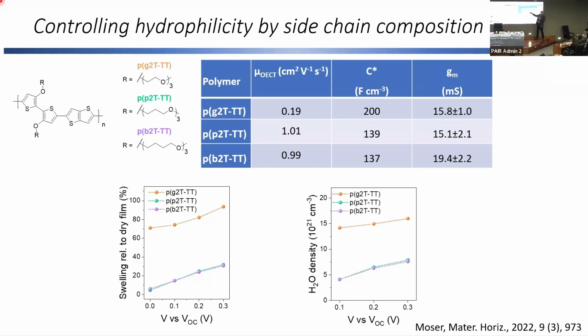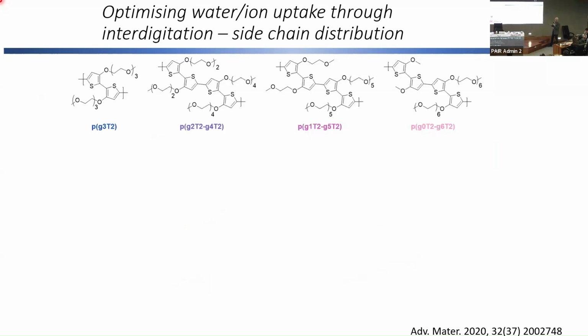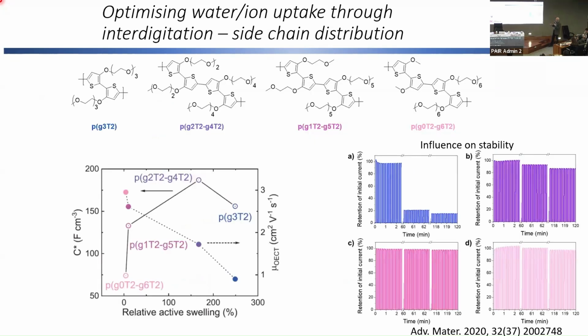Your volumetric capacitance decreases, unfortunately, but you kind of win a little bit in the end. But this is the problem with the approach of reducing the ion content: it reduces your volumetric capacitance. So this approach worked a little bit, but we then explored other approaches. Here we're introducing differences in the length of the side chains along the repeat unit in order to change the swelling by changing the interdigitation.